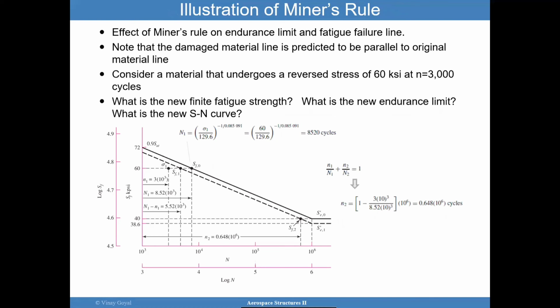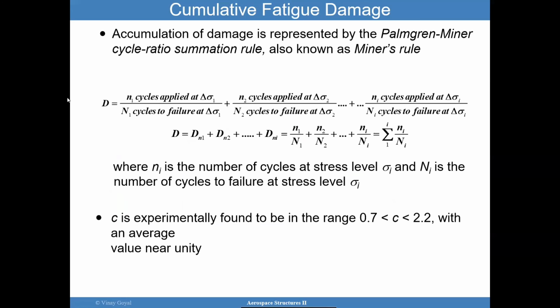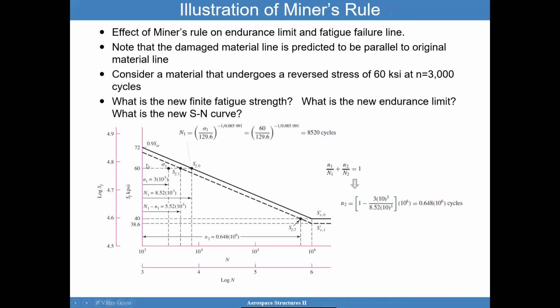And to illustrate Miner's rule, all you're really trying to do is determine, after you apply the stress at that many number of cycles, what is the new fatigue curve. That's really what you're doing with these calculations. I'm illustrating what this formula does, but it's not necessary for me to cover this because you can just use this formula to figure it out. What is important is that when you consume 60 KSI, 3,000 cycles, you consume some amount of life there. And when you do that, you naturally reduce this curve into this dashed curve as a consequence.